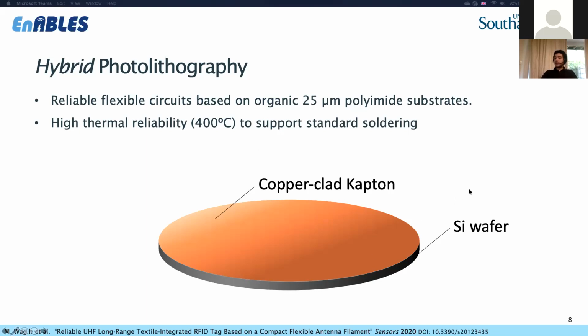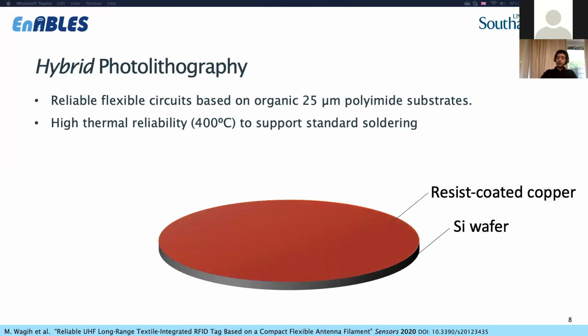The way we do it in-house for improved throughput is we use a silicon wafer just to stabilize our substrate, to keep it in place. It could be a glass substrate, it could be any surface which can withstand the process. We also use alumina tiles, and we adhere our copper clad Kapton on the surface. We spread photoresist, and instead of relying on spin coating, which is usually expensive and only available in clean rooms, we can either print photoresist directly using a standard inkjet printer, or simply paint it or doctor blade it using a roller, using the techniques Surya introduced earlier.